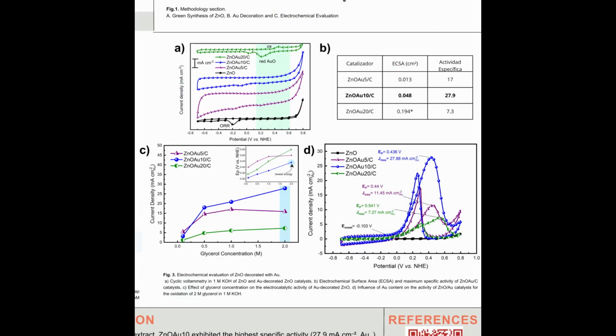Electrochemical performance. Electrochemically active surface area increased with gold content, but higher values did not guarantee better activity. The highest specific activity, normalized by gold loading, was obtained for zinc oxide gold 10 millimolar on carbon at 27.9 milliamperes per square centimeter of gold. This is comparable to the best gold-based glycerol oxidation catalyst reported. Zinc oxide gold 5 millimolar showed moderate activity, while 20 millimolar, despite the largest surface area, was less active due to agglomeration, reducing site quality and accessibility.